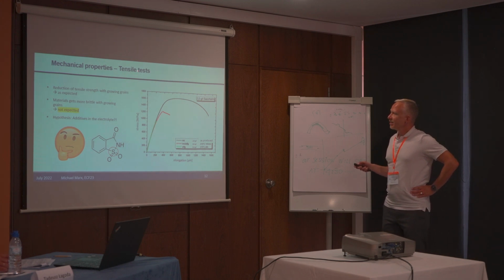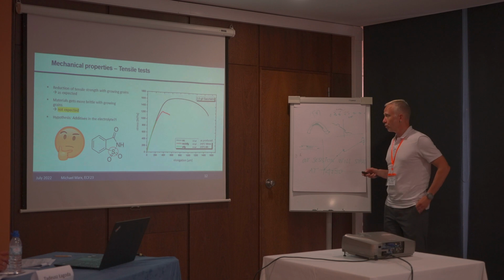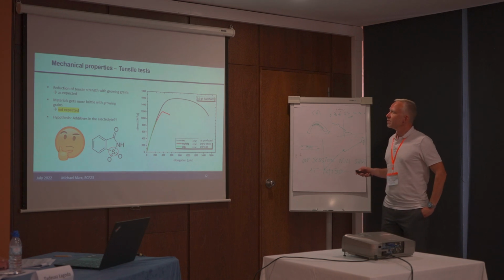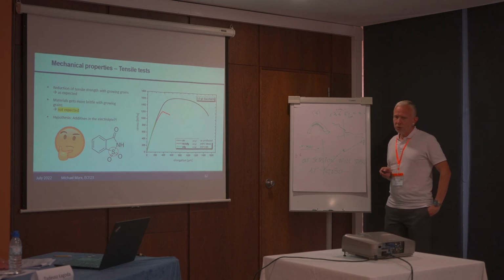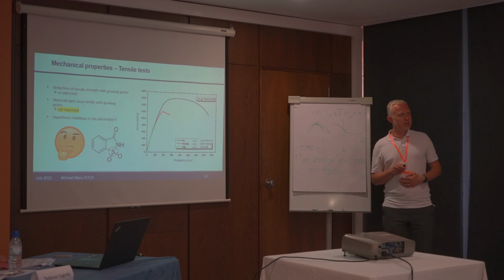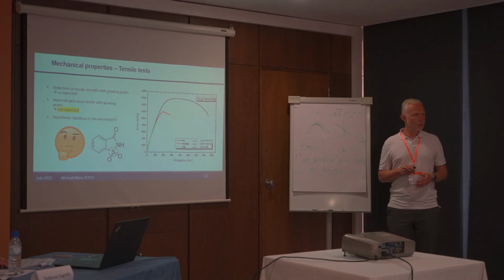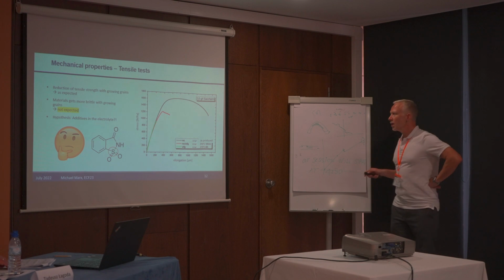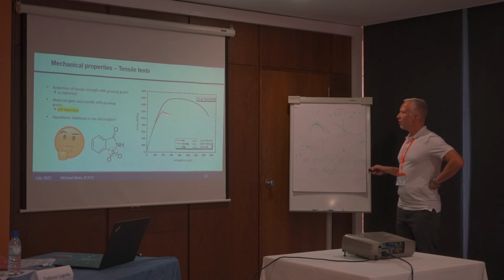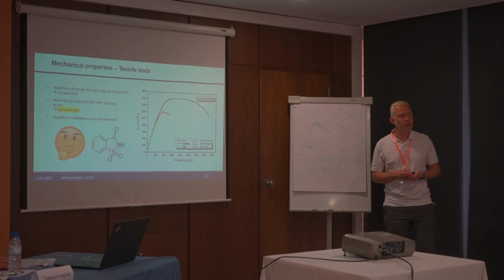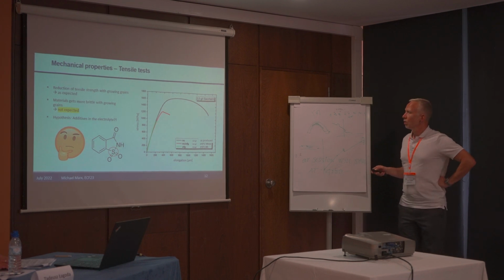What we have also done, tensile tests, and here the black line is for the nanocrystalline material as it was produced, and for the heat-treated material we expected to get more ductility because we have some larger grains. However, we have here found this red and the green curve, the red for the bimodal microstructure and the green for the ultrafine grained material.